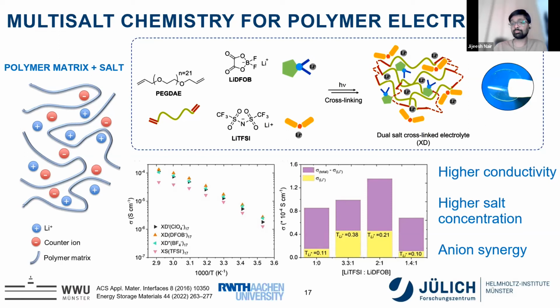But keeping that viscosity or keeping the same concentration, using a second salt, you can improve total lithium salt concentration also. And then you can play with the anion synergy, which kind of anions you use, 1, 2, or 3 different families of systems. You can combine this to have a better anion synergy to improve the interfacial property.